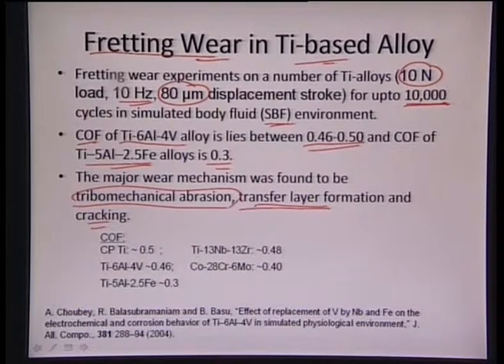And it also tells that the coefficient of friction is very high for commercially pure titanium, which was of the order of 0.5, whereas it decreases in titanium 6 aluminum 4 vanadium marginally. It showed a variance from 0.46 to around 0.5, and again titanium 13 niobium 13 zirconium showed around 0.48, whereas titanium 5 aluminum 2.5 Fe showed around 0.3, and cobalt 28 chromium 6 molybdenum showed around 0.4 of coefficient of friction.